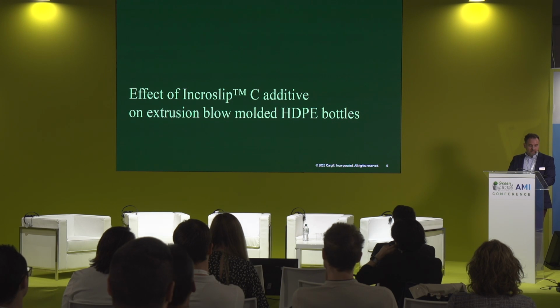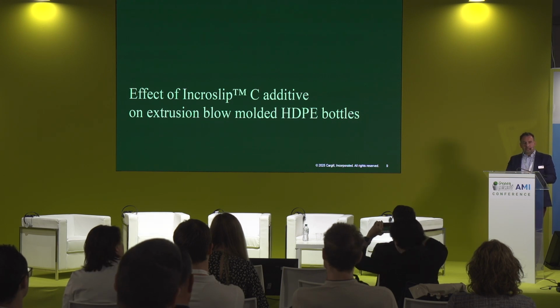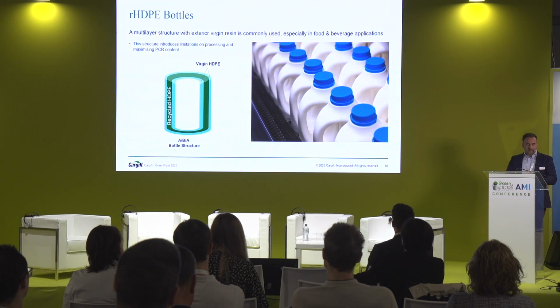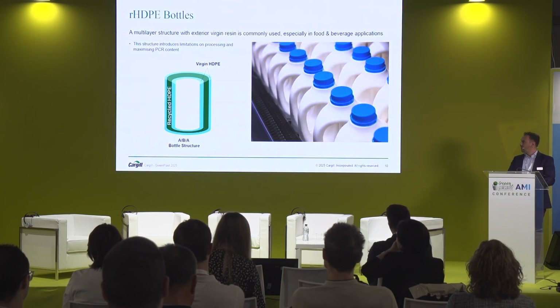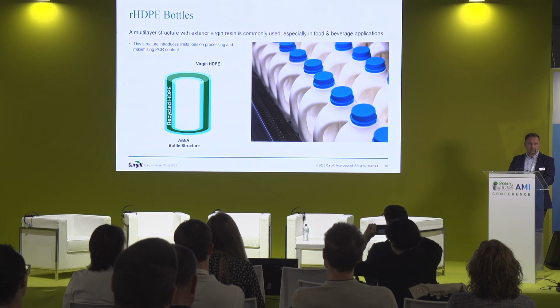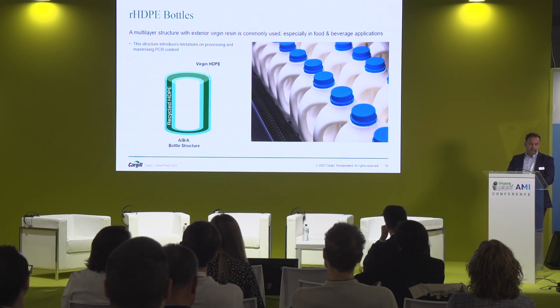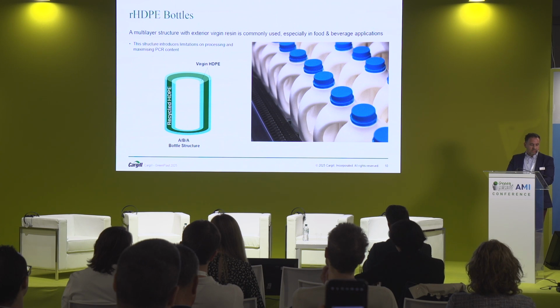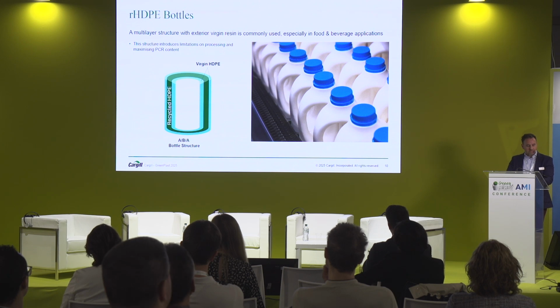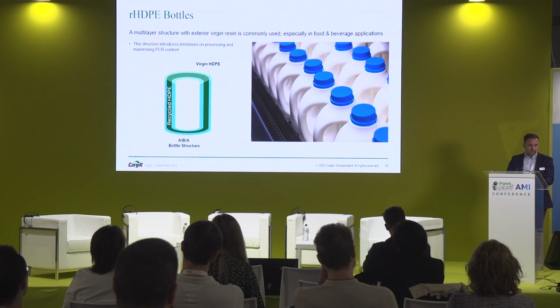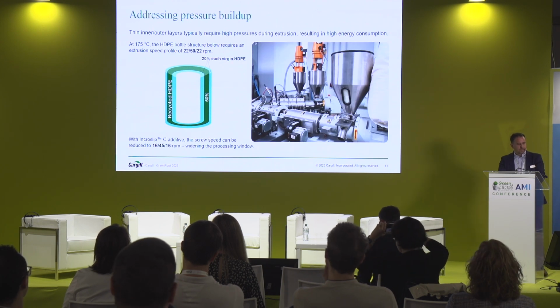So we started by investigating the effect of the additive on a product, and ideally a product that can be easily recycled, and in the UK, for example, is one of the prime examples of closed-loop mechanical recycling, using and reusing the milk bottles. So we did a series of tests using an extrusion blow molding equipment and an ABA bottle structure where the middle layer is recycled HDPE and the inner and outer layer virgin HDPE. And we added in the inner and outer layer the additive, our additive, which is Incroslip C, via master batch.